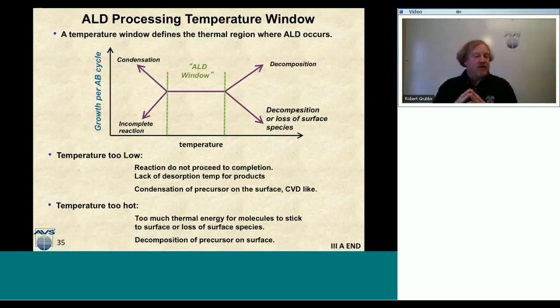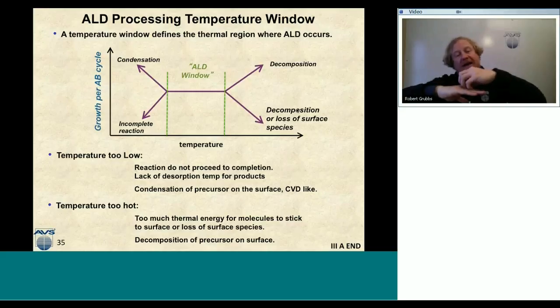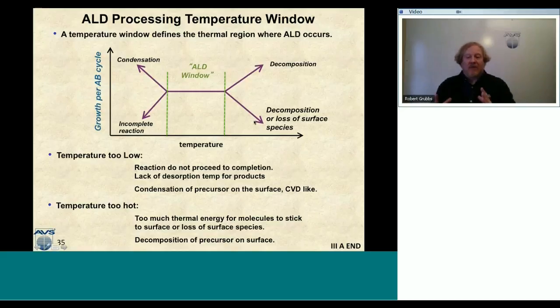If my temperature is too hot, the precursor that comes down, maybe I need that precursor to be in a physisorbed well, but it's too hot, and that precursor just desorbs right away. So I'll see a decrease in the growth per cycle as a function of temperature if I'm too hot, if I'm outside the temperature window. So these are the two regimes of ALD, and this temperature window can vary wildly between different chemistries.